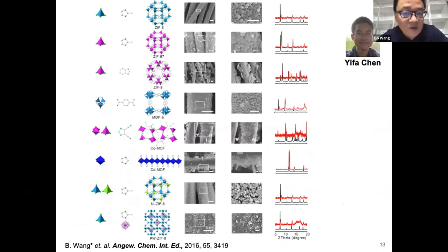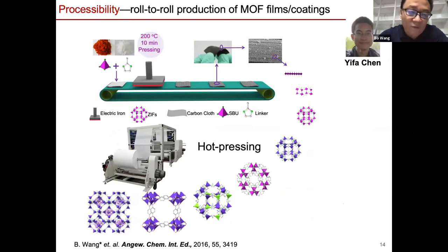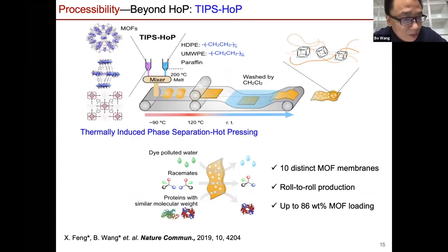We can grow some easy MOFs on different structures, different surfaces, very easily. And since it's a very simple method, in this case we start from the powder and through hot pressing, you can grow on the fabric. Using this method, we can go all the way to roll-to-roll production, because from one side you cast the powder on the surface, and from the other side, the hot roller rolls on, and eventually gives you different types of MOF nanocrystals covering the surface of different substrates. We succeeded in making those in large quantities. We are making this nonstop, like 100 square meters per hour of this MOF coating on different substrates using this method. We further combined this method with a traditional membrane method, which is the thermally induced phase separation process.